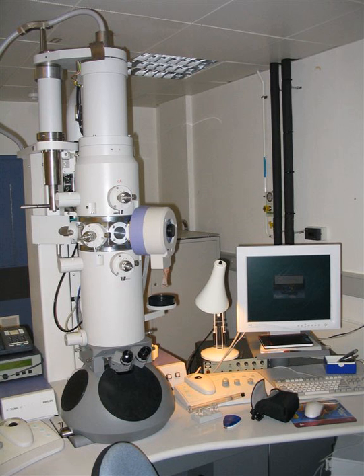Typically, thin sections are stained for several minutes with an aqueous or alcoholic solution of uranyl acetate followed by aqueous lead citrate. Freeze fracture or freeze etch, a preparation method particularly useful for examining lipid membranes and their incorporated proteins in face-on view. The fresh tissue or cell suspension is frozen rapidly, cryofixation, then fractured by breaking or by using a microtome while maintained at liquid nitrogen temperature.